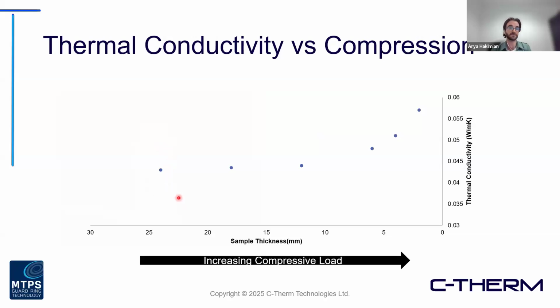And as I highlighted, the effective thermal conductivity can be impacted by that level of densification. As we increase that compressive load on the sample, squishing it down more and more, we can typically see a trend of this nature. This was on an insulation sample, where as we increased that force load more and more, we started to get a higher thermal conductivity. For insulation, of course, we typically want to target a low thermal conductivity, which would correlate to a higher thermal resistance. But understanding how that material will behave under those different states can be quite informative in determining what your breakpoints are in the setup and the design of those systems.